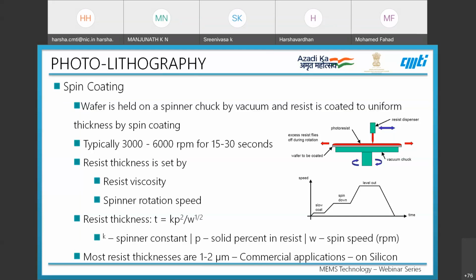So how do we arrive at the resist thickness? The resist thickness can be arrived at by two parameters: one is the resist viscosity and the rotation speed of the spinner. The resist thickness can be defined as T equals K times P squared over the square root of W, where K is the spinner constant, P is the solid percent in resist, and W is the spin speed.